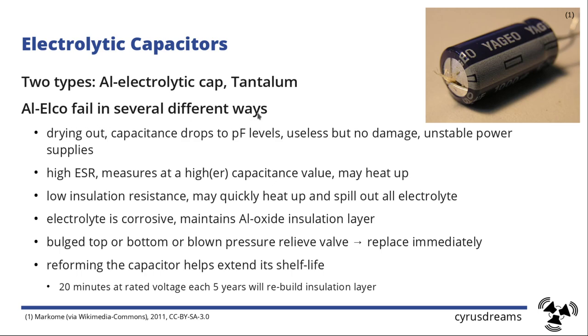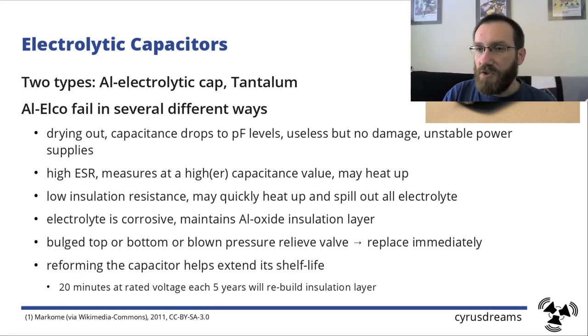They have several different failure modes, interestingly. They do dry out completely without bursting and spilling everywhere. The water-based electrolytic solution in there will evaporate over the years, and the remaining capacity is just a few picofarads. The whole capacitor is useless, but it does not damage a board. It can, however, lead to unstable power supplies. So eventually you should replace them, of course.